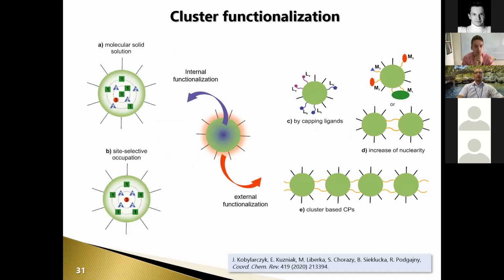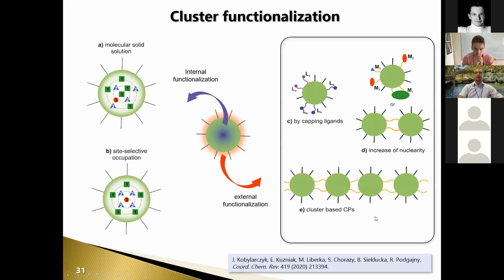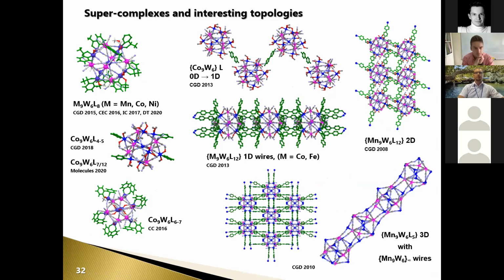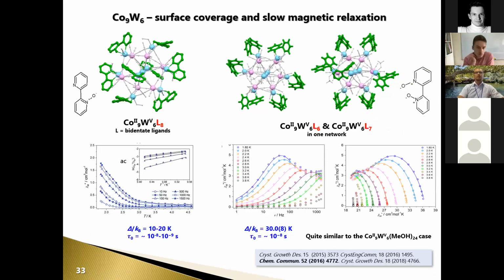Okay. And coming back very quickly, because I'm short of time, for the external functionalization, we can do it by capping ligands, by increase of nuclearity, and the formation of cluster-based coordination polymers. Using this approach, we obtained quite a lot of interesting topologies. The most important issue here is that with cobalt tungsten cluster and such ligands, we obtained the network where two clusters are shown, one with 6 ligands around and one with 7 ligands around.